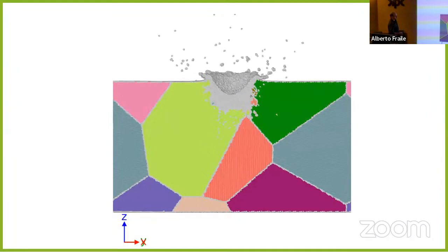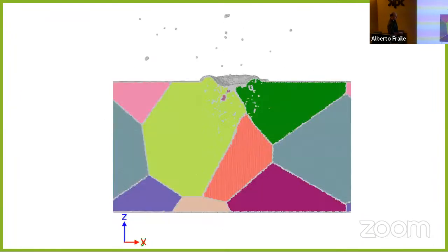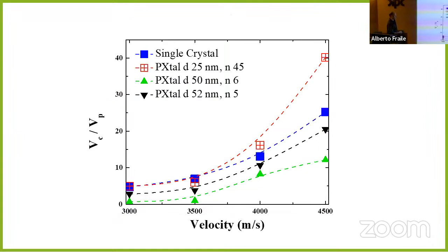The thing is that if the kinetic energy is not that high, well, you are only touching probably 2 or 3 nanocrystals, so the rest are not really affected, but you see differences. For example, here you see that the crater has this asymmetry in this cut, so it's not semicircular like before. It depends on how the polycrystal is. So one should do a lot of simulations to have really statistics and everything, but right now we have some results, and the single crystal case is the blue squares. Polycrystal with a lot of nanocrystals, it's more or less the same, although here it presents higher values for the volume of the crater, and for a small number of crystals, so big nanocrystals, we have lower values for the volume. So we are analyzing this, repeating more simulations to have this clear, because maybe it depends.